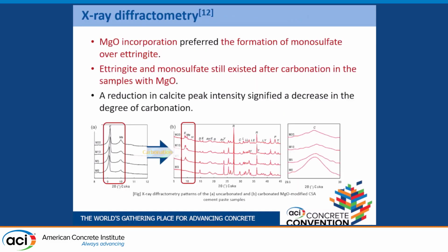So these are XRD results of uncarbonated and carbonated samples. As you can see, the magnesium oxide incorporation preferred the formation of monosulfate over ettringite. And upon carbonation, the ettringite and monosulfate still exist after carbonation in the samples with magnesium oxide. On the figure on the right, you can see a reduction in the calcite peak, which signifies a decrease in the degree of carbonation.